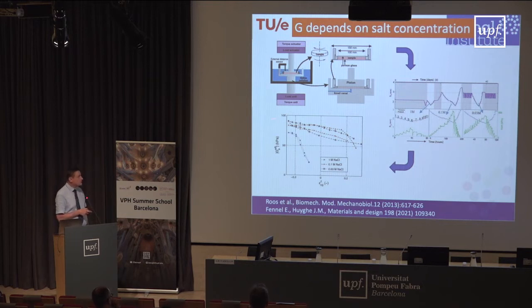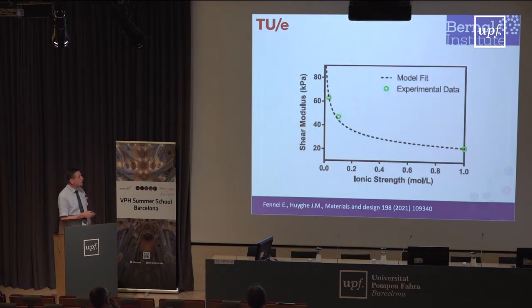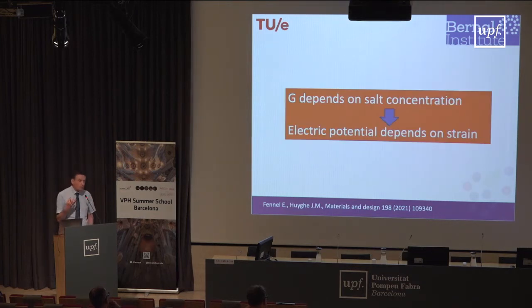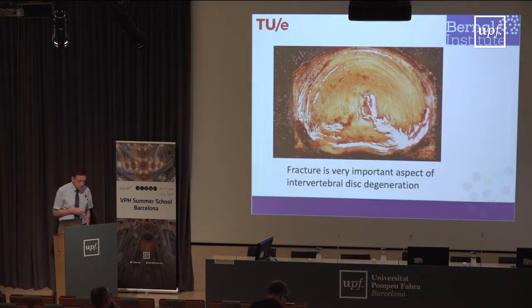And so this kind of result has been found by us for gels, but by Alan Grodzinsky at MIT for cartilage. Here we have a dependence of stiffness on salt concentration as such. And you see here shear modulus plotted versus ionic strength, and you see quite significant changes in stiffness. All of this we can build into the model so as to represent really what is happening in such a gel. And automatically, when you assume the shear modulus to depend on salt concentration, also electric potential depends on strain, which may be extremely relevant to mechanotransduction as well.